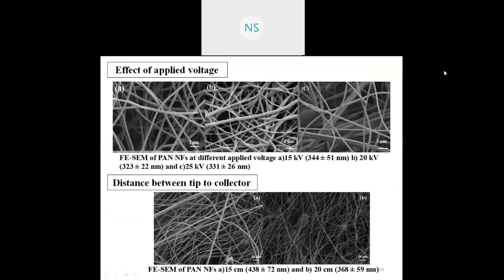Whatever we have mentioned, that is the applied voltage, we are applying the voltage to the needle tip from 10 to 30 kilovolt. What will be the effect of that particular voltage over the size? When we apply 15 kilovolt, it gives 344 plus or minus 51 nanometer, means nearly 350 nanometer of the fiber. When you apply 20 kilovolt, it gives 323 nanometer size of fiber, and at 25 kilovolt, 331 nanometer size is possible.